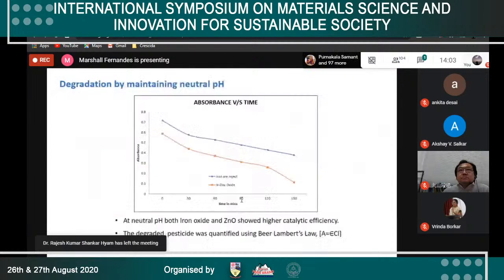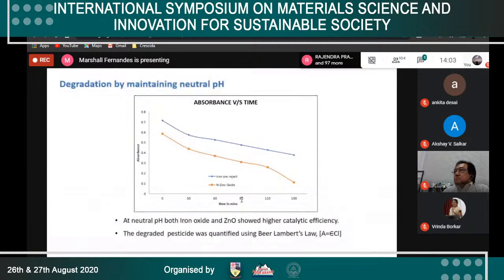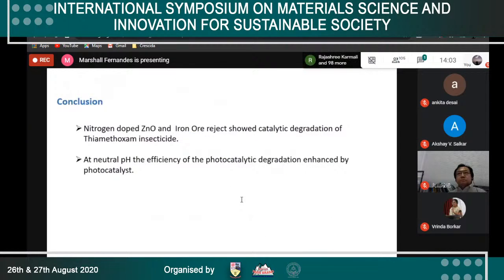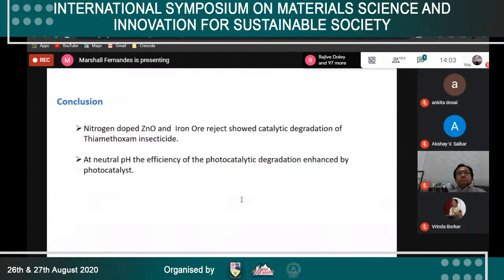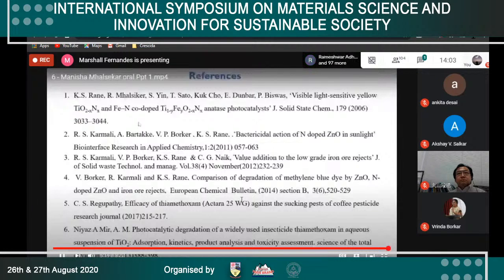Degradation by maintaining neutral pH. Similarly, it was observed that zinc oxide was found to be more effective in degrading the thiamethoxam at neutral pH as compared to degradation carried out using iron ore reject. So from this, it was concluded that nitrogen-doped zinc oxide and iron ore reject showed catalytic degradation of thiamethoxam insecticide. At neutral pH, the efficiency of photocatalytic degradation is enhanced by photocatalysis. Thank you.